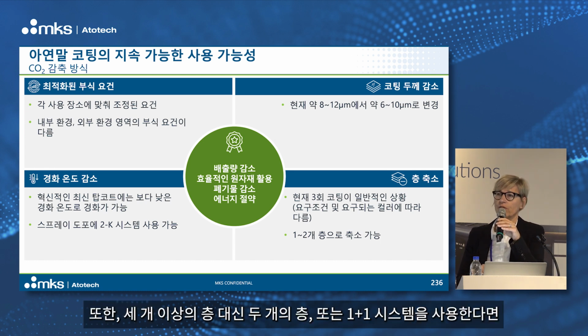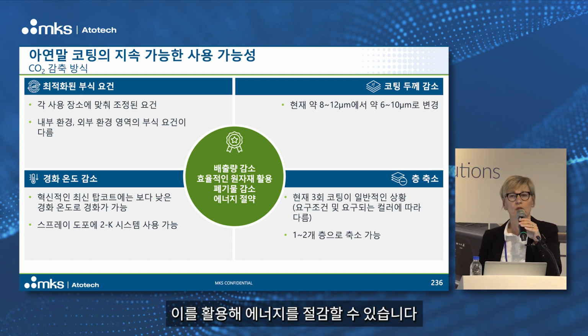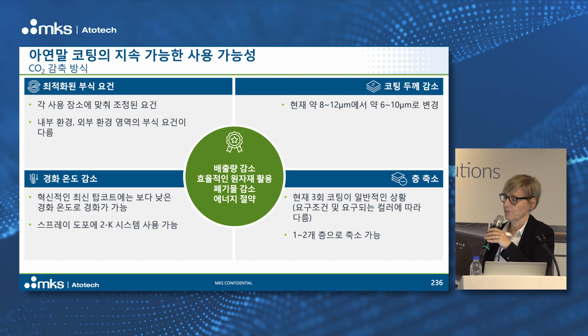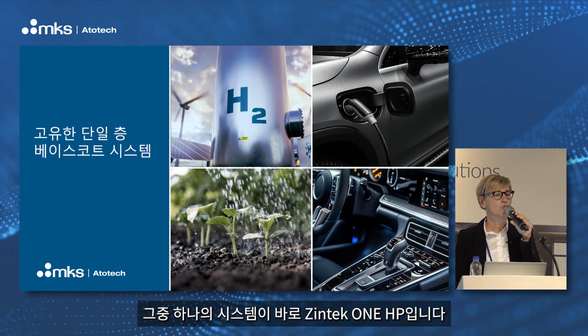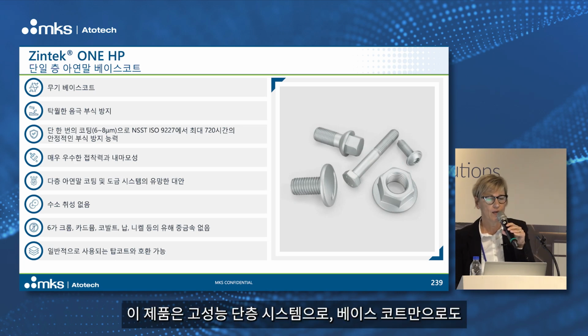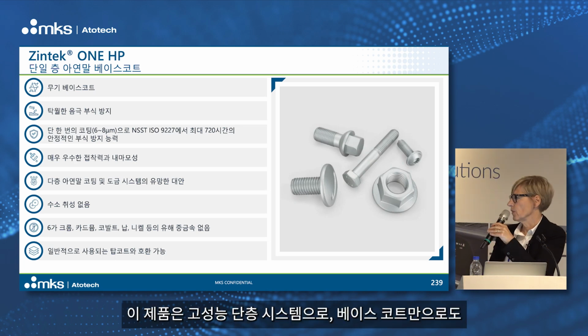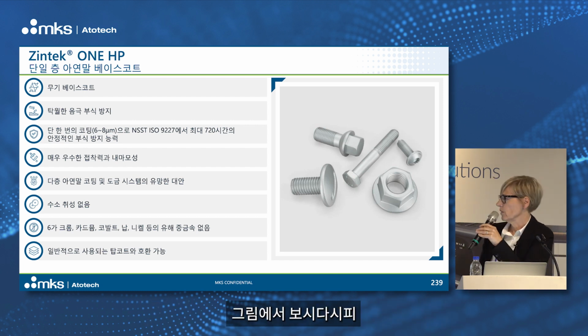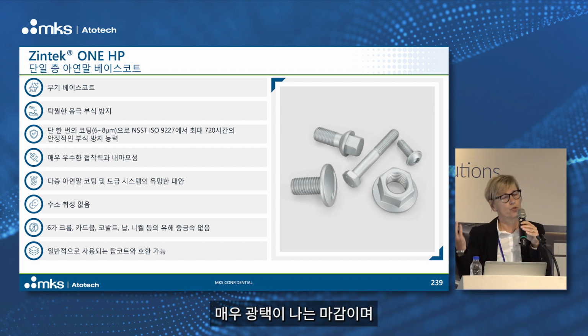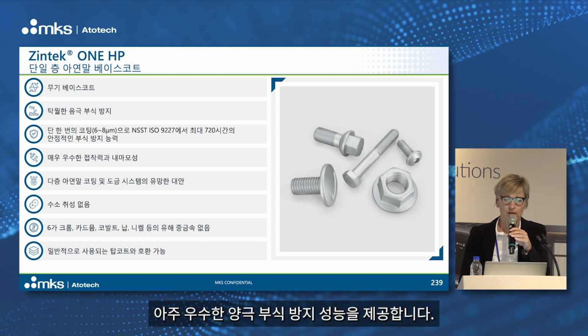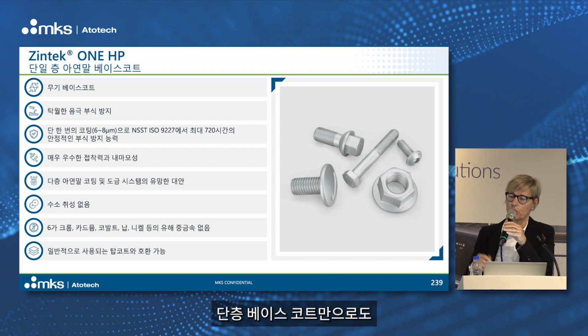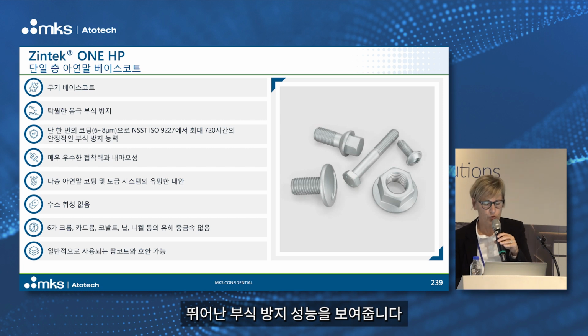And of course, if I can reduce the layers, instead of having 3 or more layers, only having 2 layers or 1+1 layer, why not use this advantage? One system where we could achieve that is Zintek ONE HP. That is a high-performance one-layer system, the base coat. In this base coat, you see the picture, it is really looking like this. It's a shiny finish, has still very excellent cathodic corrosion protection. And with this base layer, you can already achieve very nice corrosion performance.